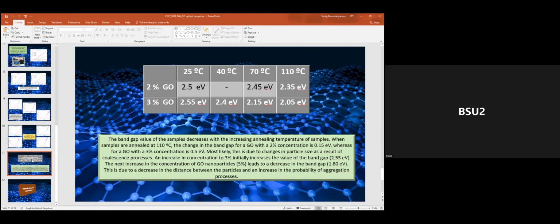Whereas for a graphene oxide with a 3% concentration it is 0.5 electron volt. Most likely, this is due to change in the particle size as a result of coalescence process, and increase in concentration to 3% initially increases the value of the band gap, 2.55 electron volt.